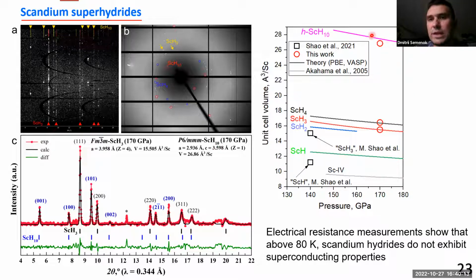The hydrogen content we calculated by comparison with the theoretically predicted equation of state for scandium H10. You see, this is a hexagonal scandium H10, and it's probably the P6/mmm structure, and this is our structure. It's quite close, and approximately we can say that this is scandium H10. To not make the result too complicated, for simplicity, let's just call it scandium H10. For the other compounds, as I told you, the volume of scandium H4 is in agreement with theoretical calculation. The volume of scandium H3 is also in very good agreement with theoretical calculation.